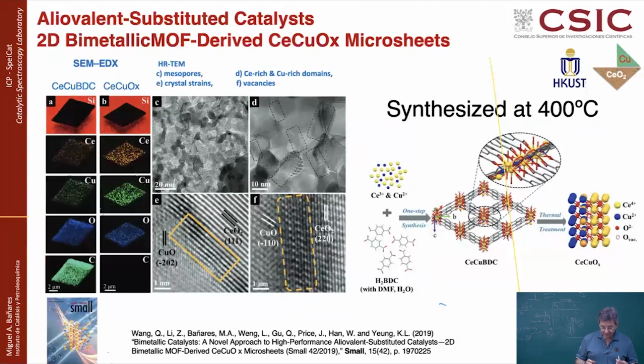Now the idea is, because this is working very nicely, can we use other metals that are more economic to activate and to amplify this oxidation capacity of cerium? And then we were looking at copper, which is probably a very convenient element, very good for combustion, and much more economic. And in this case, we were also using another benzene dicarboxylate precursor. Then we were getting platelets like this.